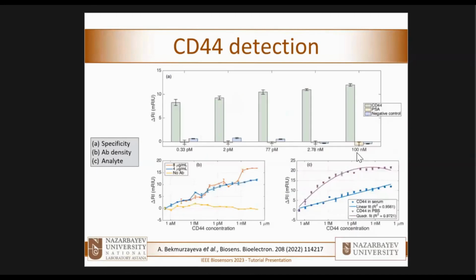Again, we have tested the specificity using methods that are quite standard. And we even tested the response in different media, such as in serum or in PBS, to evaluate basically the differences. And in general, the sensor tends to have a log linear pattern in serum, but a quite saturated pattern in PBS. Again, that's quite common in all optical fiber biosensors. So it's not a perk of this one, but it's quite common even on the methods that are not so minimalistic in terms of fabrication.